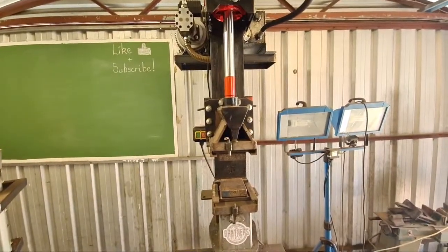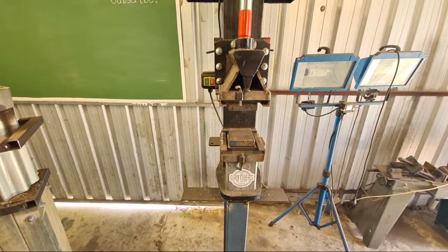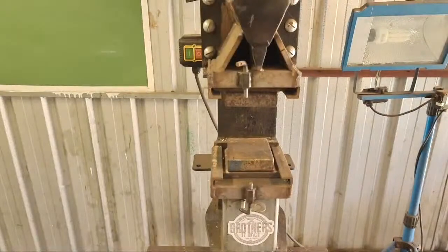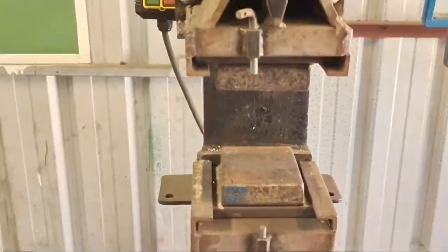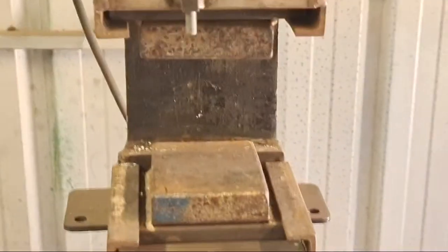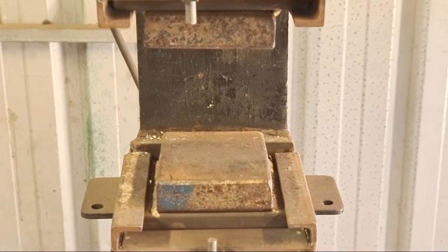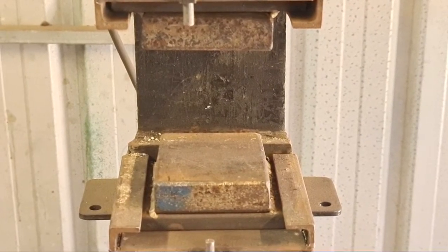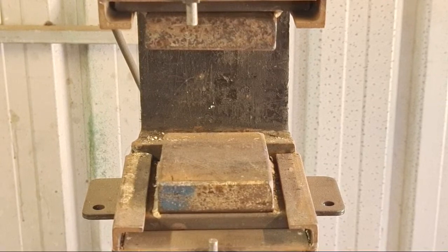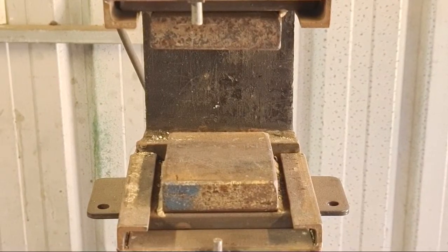Yeah, 1084, 15N20 mix. The 15N20 is 2.5 millimeters thick. The 1084 is 3.2 millimeters thick. So 15N20 is basically 1075 or thereabouts, but with a whole bunch more nickel. 15N20 is commonly used in industrial bandsaw blades for woodworking workshops because the nickel increases its stain resistance. So it's basically 1075 with slightly higher stain resistance.